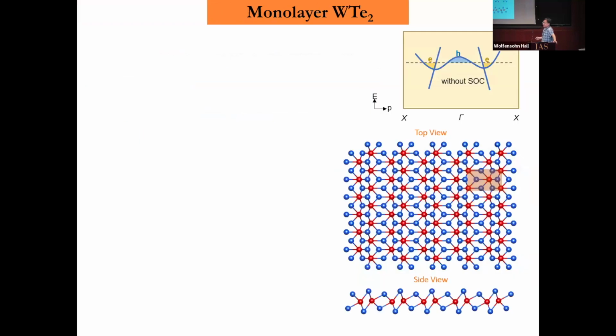Okay, so this is a material that we have worked on for several years now. I studied this material, the monolayer. Bob Cava grew this material here at Princeton. It's a big bulk crystal, allowing us to exfoliate monolayers. I've worked on creating monolayers of this material since 2015-ish, and we really see a lot of interesting phenomena in this material. This is a 2D crystal which has a lattice structure like this, and the red ball is tungsten, the blue is tellurium. It's a TMD, transition metal dichalcogenide.